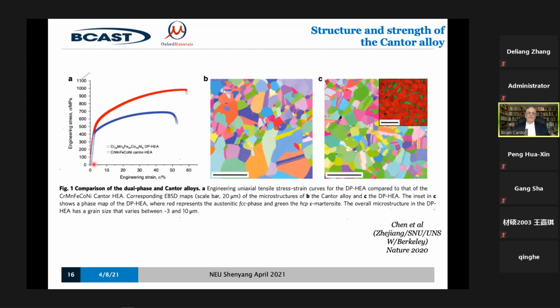But the unusual feature, it turns out, is that it's got very high strength. So face-centered cubic copper or gold or aluminium has a strength no higher than about 100 megapascals, and then a lot of ductility. And we work very hard to make it have higher strength, but that always restricts the ductility. Because this is face-centered cubic, the ductility is still 50 to 100%. Initially, it's very, very high strength. That's why people recently have become very, very interested in this material.